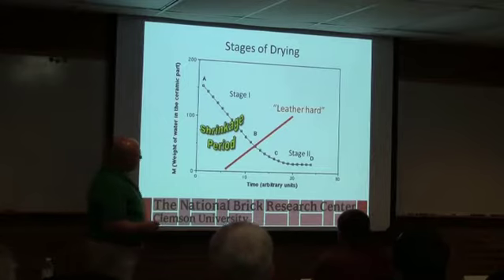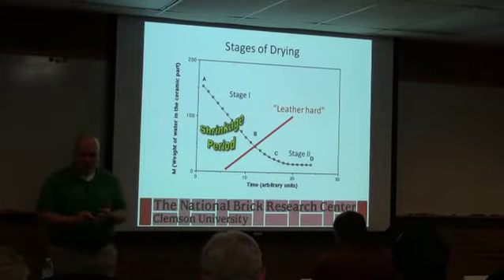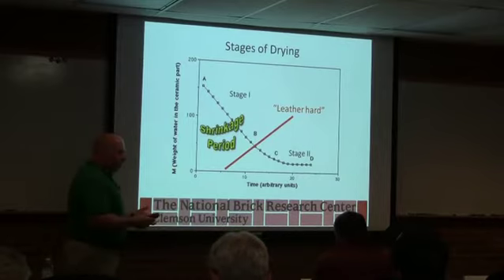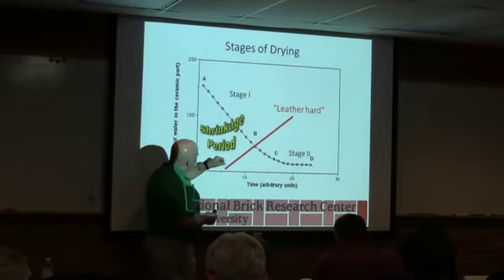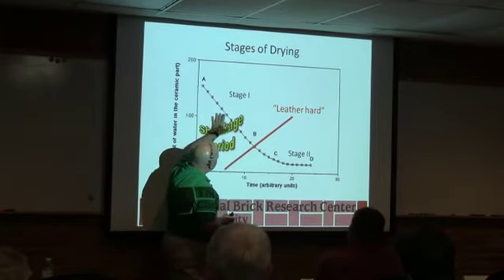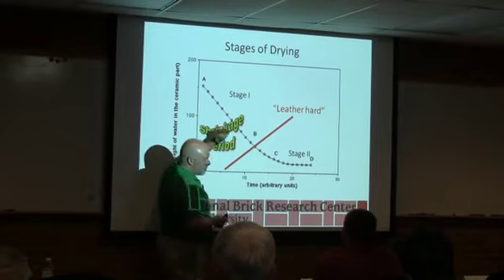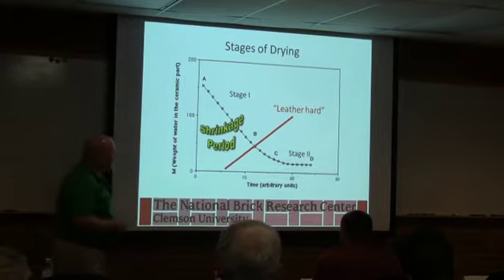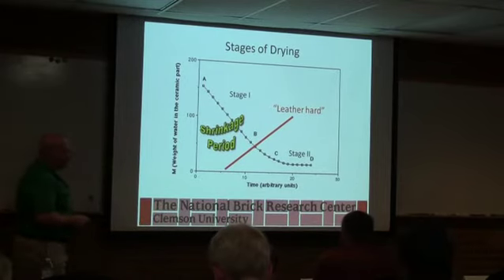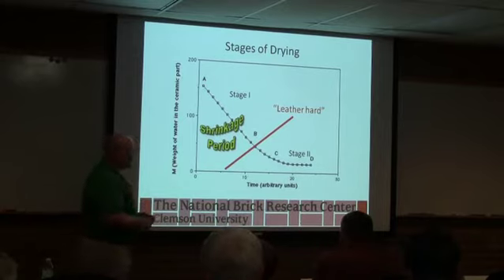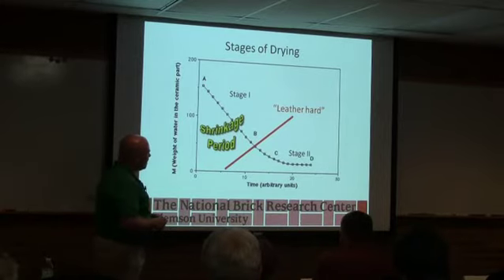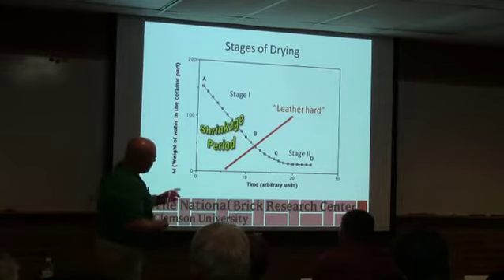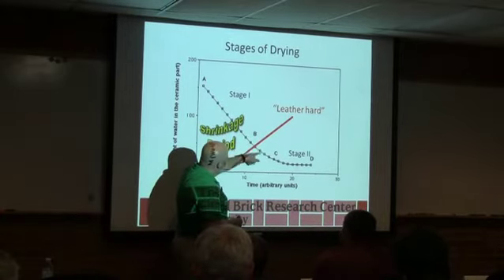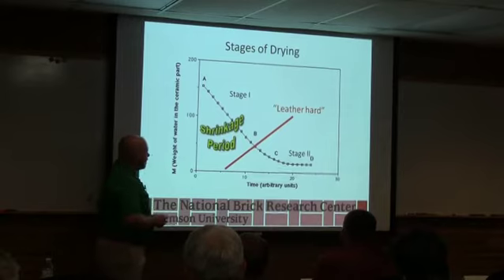So when we're looking at these stages, remember we talked about how the different types of water do different things. There are different stages of drying that correlate to those types of water. Typically we talk about stage 1 as the initial stage of drying, and it's the stage where all the shrinkage happens. And it's pretty stark. You can see this in drying curves. There's also an easy way to tell where this happens in your brick. I think I've got an example I'll show you. But just by putting a thermocouple on the surface of the brick, you can tell where it transitions out of the shrinkage stage. And I thought I'd discovered something pretty interesting.